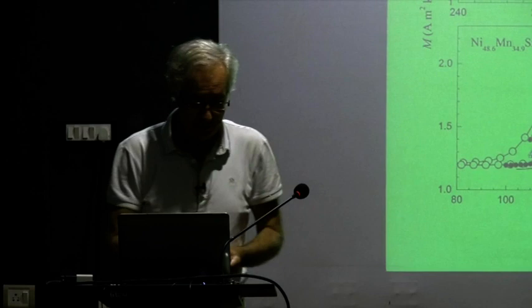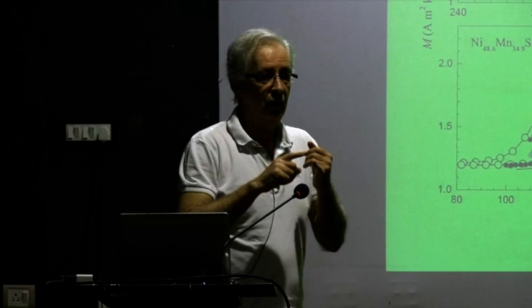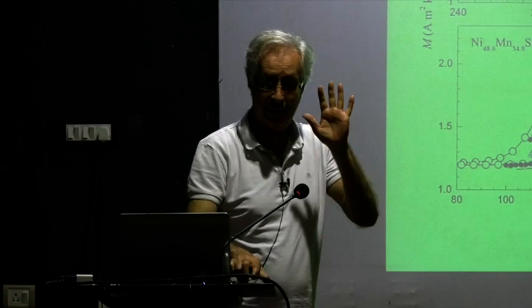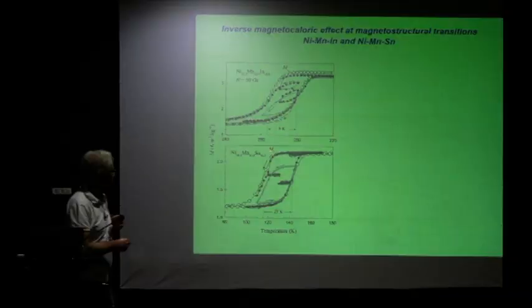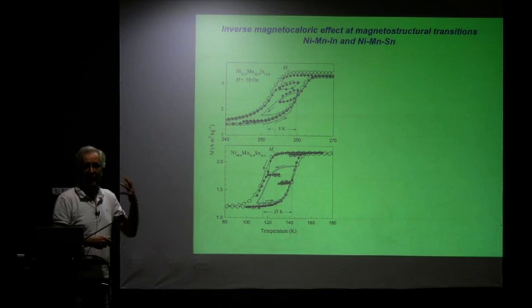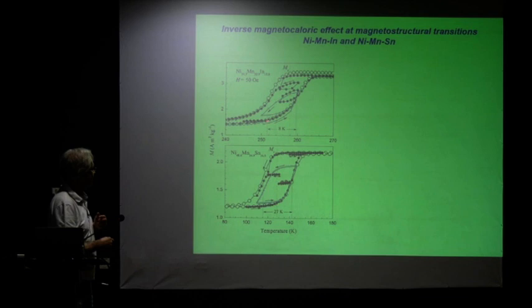It turns out that when we decrease and increase the temperature, we cannot change the state of the system. There is this one particular thing about hysteresis: when you're going through loops or back and forth in temperature, there are two cases. One is you don't change the state of the system. Two, you change the state of the system. These are the two basic things which are important for the magneto-caloric effects. When everything is going back and forth on the same curve, the system gets stuck in a certain state — a lot of martensite and a little bit of austenite — and the state will not change until we increase the temperature further.